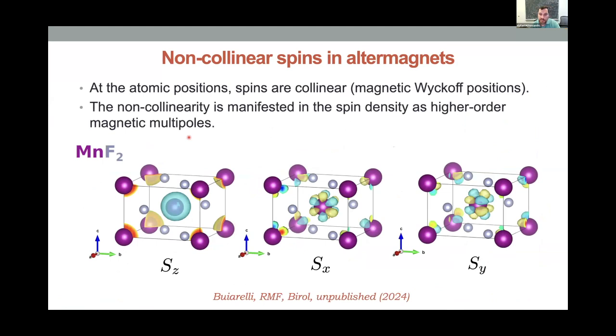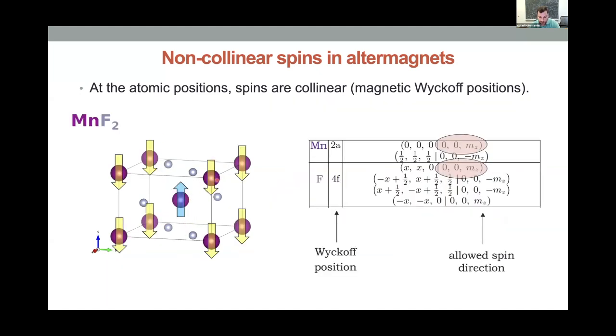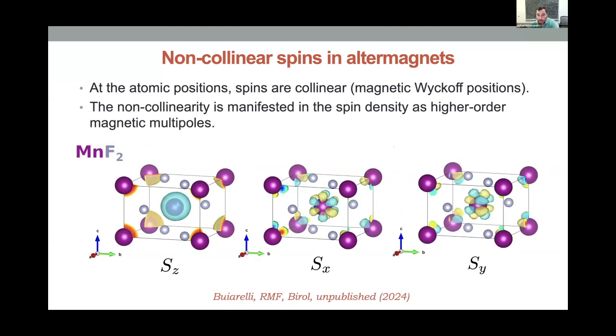Well, this non-collinearity, actually, you can see if you look at the spin density rather than the spin value at the point. So this is a calculation that we did in collaboration with Turan Birol, a DFT calculation for manganese difluoride, showing the spin density for different components. You see very nicely these essentially spherically symmetric dipoles for SZ. This comes back to this figure here. But you see now that for SX and SY, you get a non-zero spin density that has several nodes. It actually has properties of a multipole moment, and they're present. Of course, if I look just at the atom, it's 0, but around it, I have a finite spin density. Okay?